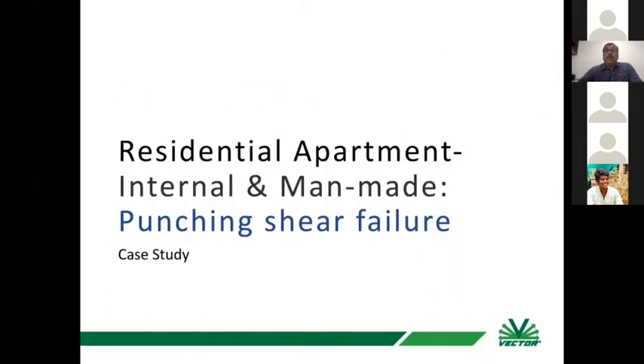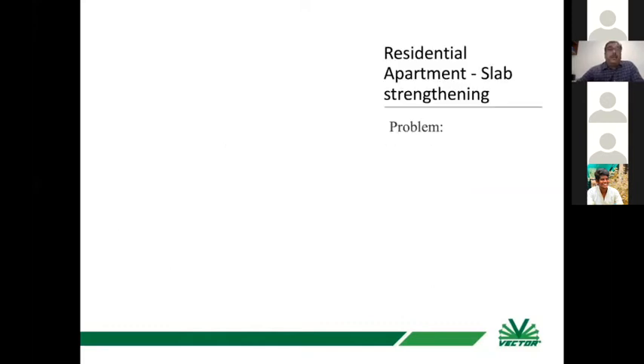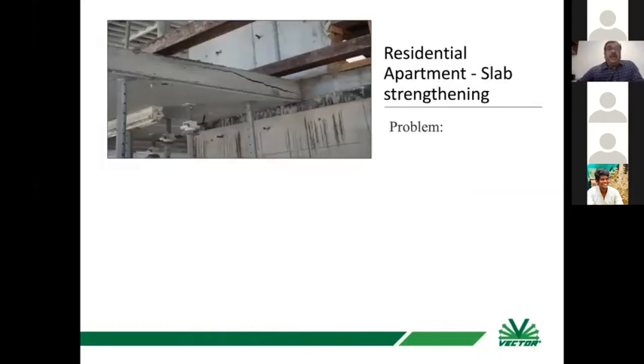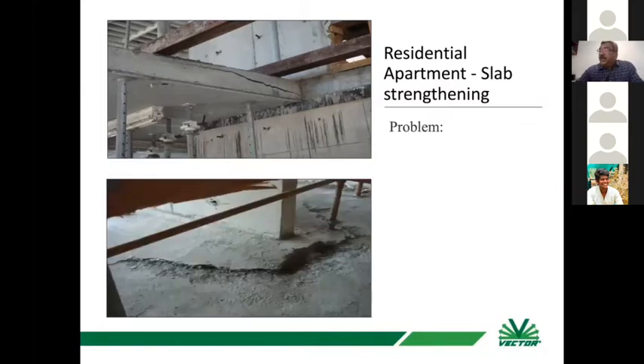I will just have a few slides for a typical failure which is not a corrosion effect. It's a design problem. When the building was under construction, there was a typical punching shear failure. You can see the shape of failure. This is because a person forgot to mention the required steel in the drawing, and this led to such type of failure.